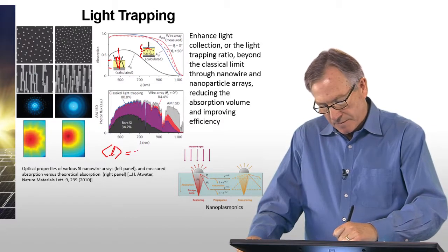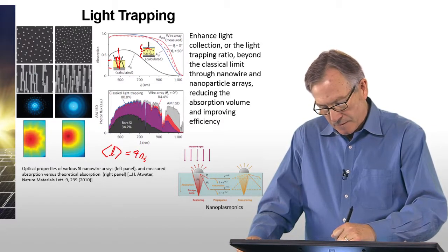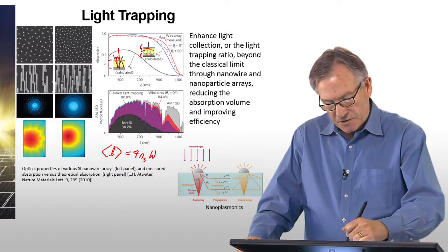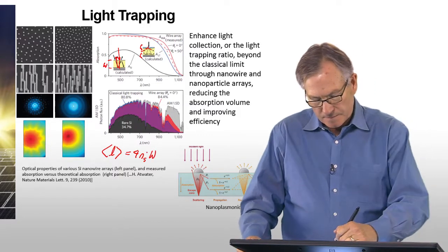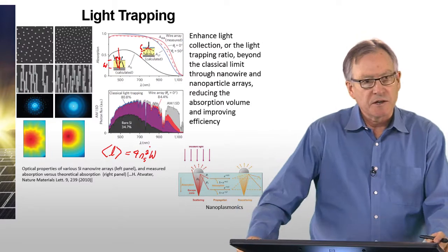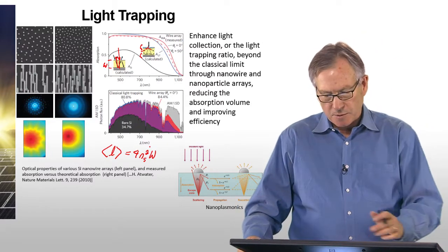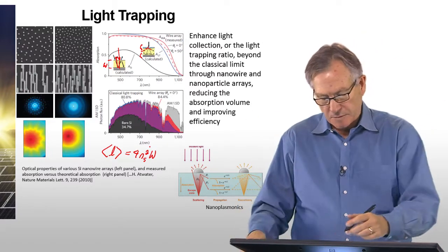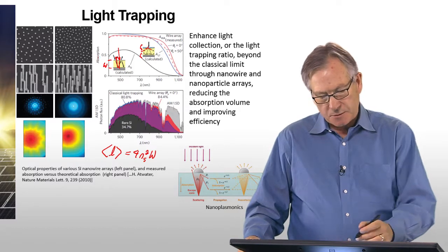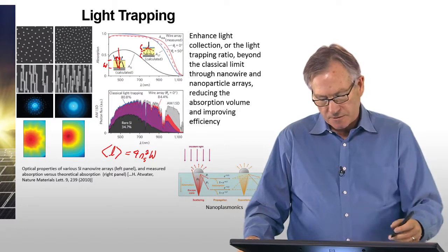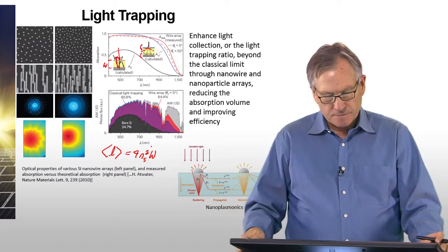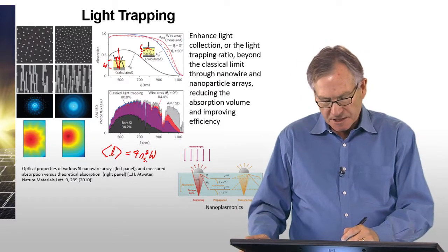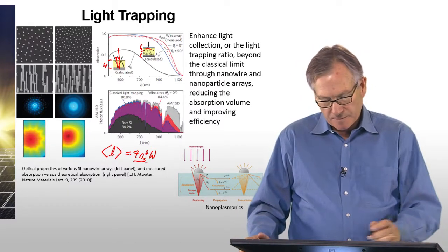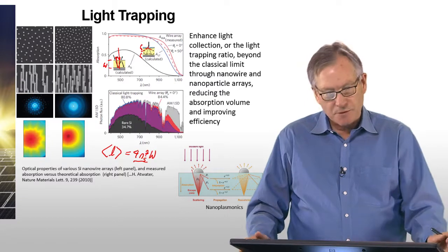And that classical light trapping limit is basically that the effective path length, if this is a width W, the maximum enhancement of the path length that you can get from a totally random scattering from the surface is 4 times the index of refraction of the material itself and the width of the material. So basically the enhancement is 4n squared times the normal width W.